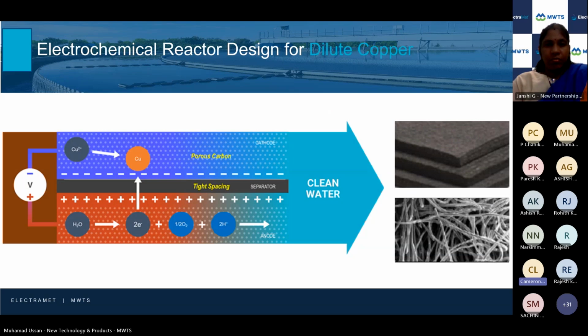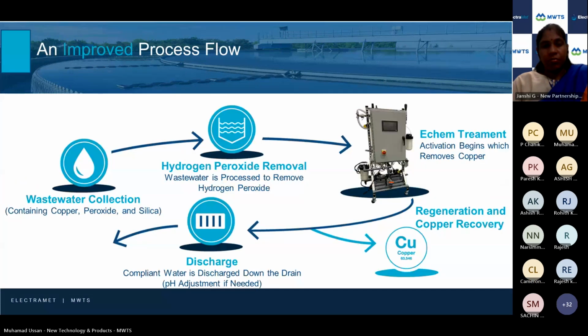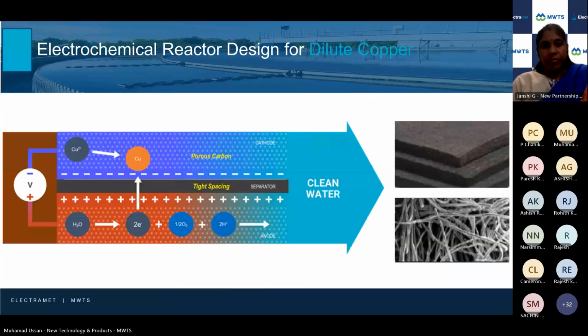And we've been able to do this by taking the lessons learned from electrowinning, taking those core concepts of how to plate metals, and modifying the reactor design to make it more efficient at lower concentrations and more selective. So we use a porous carbon cloth cathode, you can see in the picture there, and that is where the water is flowing through. So now you have a lot of high water-electrode contact area, which overcomes mass transfer limitations, and that allows you to hit the lower concentrations in the effluent. So we put this in a complete system.